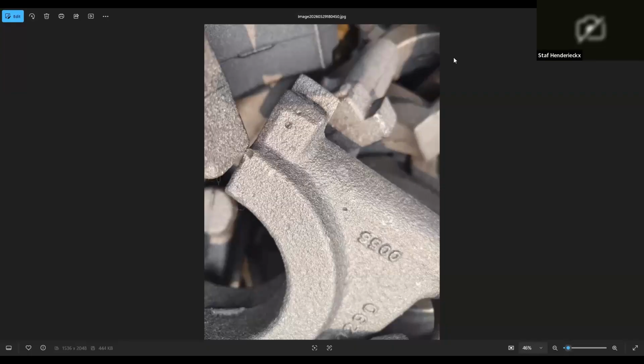The ramming of green sand is very, very, very important. Why? If the ductile iron is solidifying, at a certain moment it expands, when the carbon is coming out to form nodules. And that expansion, depending on the section thickness of the casting, is mostly higher than the strength of the green sand. If that strength of the green sand is low, it will be pushed out somewhat, and you lose extra volume that cannot be compensated later anymore.